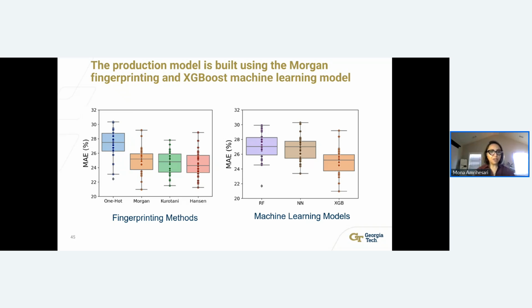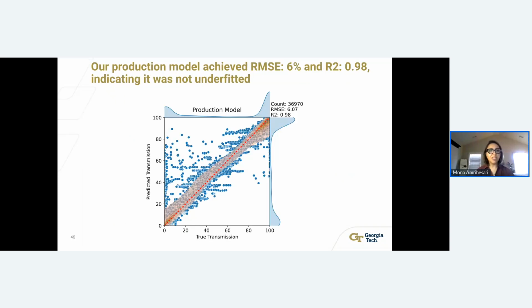Then after we set the fingerprinting system, we tested different machine learning models: random forest, neural network, and XGBoost. In comparing these three different machine learning models, XGBoost has a lower mean absolute error, meaning that the prediction is more closely matching the reality of the experimental data. After that, we built our production model, which has the RMSE, root mean squared error, of 6%, meaning that the model can predict the transmissivity of a polymer solution within an error of 6%. And the R squared is 0.98, close to 1, indicating that it's not underfitting.